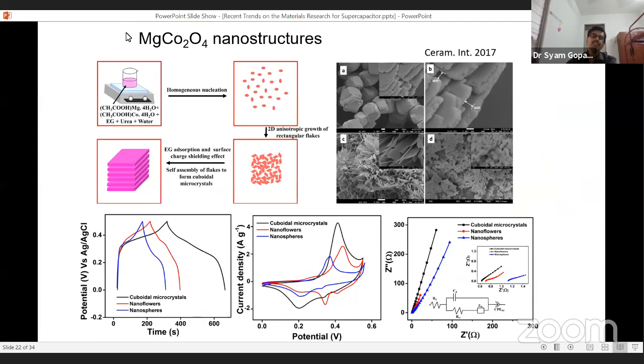Then we have also synthesized several magnesium cobalt oxide nanostructures through a simple hydrothermal technique, with several morphologies like cuboidal microcrystals, nanoflowers, and nanospheres. We synthesized different materials, and what we have observed is that these materials also have some utility for this supercap-battery research.